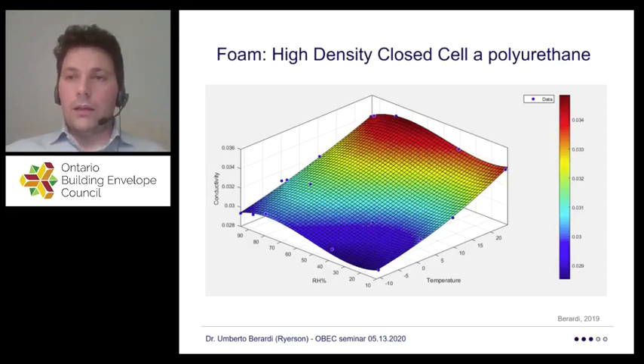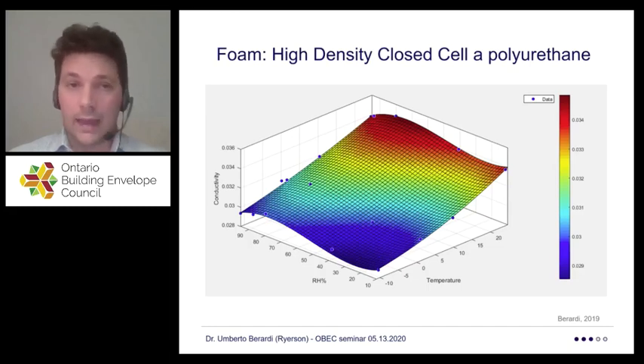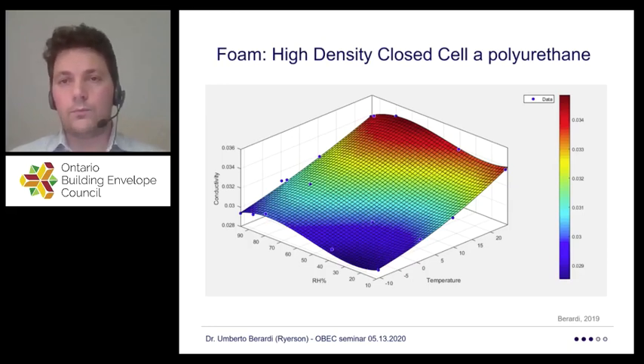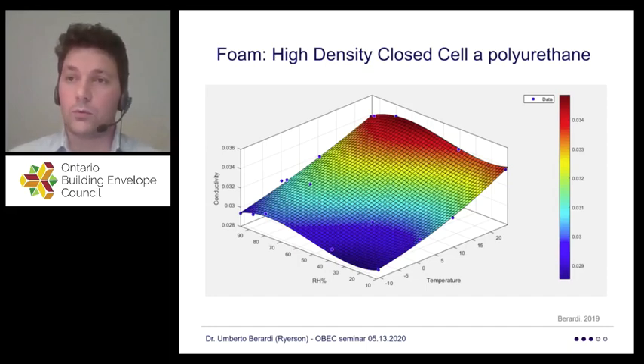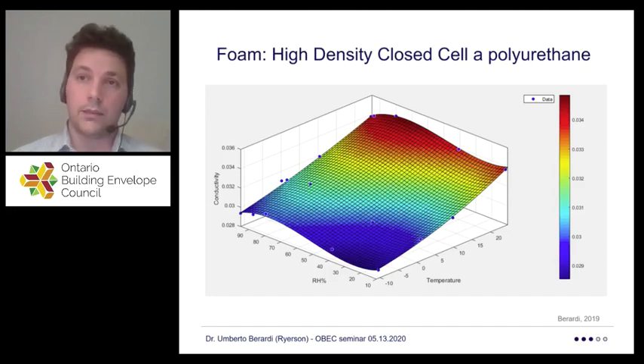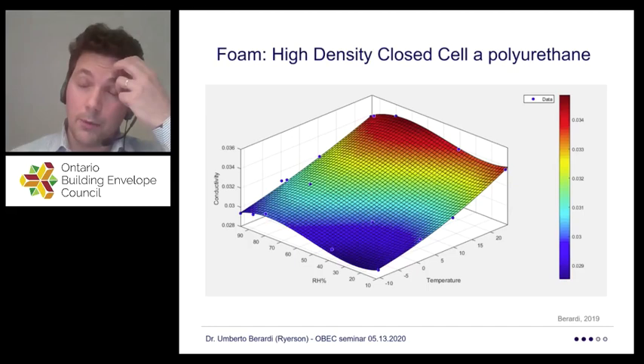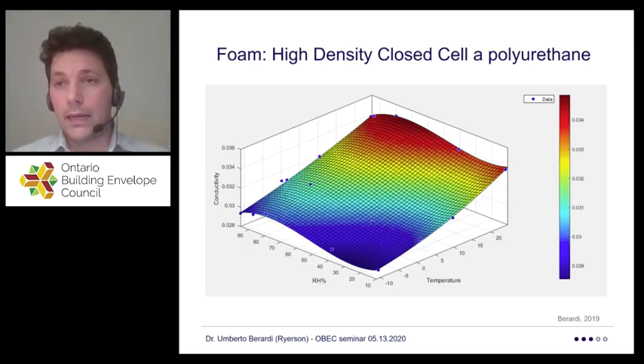So first of all, at the end of these long multi-year projects, we have been able to generate, for a lot of products, really a lot of products, 3D shapes of thermal conductivity on the z-axis in this graph, versus relative humidity and versus temperature. What that means is that in a lot of simulation from a decade ago, thermal conductivity was flat, a constant. The thermal conductivity of a closed cell polyurethane would be a number like 0.03 W/m·K. But in reality, a product like polyurethane tends to be more thermally conductive at high temperature, and less thermally conductive at low temperature. And when it comes to relative humidity and moisture content, it tends to have a Gaussian distribution, where at one point it starts to absorb a lot of moisture and the thermal conductivity becomes quite a bit higher.